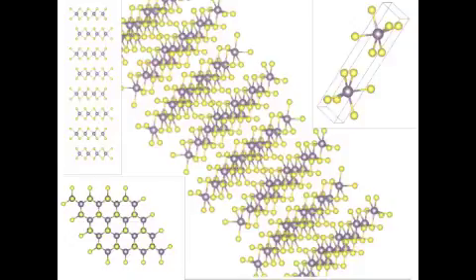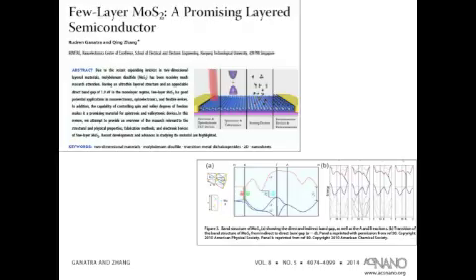There's a lot of interesting things about molybdenum disulfide as a 2D material. There's a lot of interesting ideas people have for building devices with it and how to use its layered structure because you can tweak its band structure in a lot of different ways, including based on the number of layers. Monolayer MoS2 is a direct bandgap material whereas multilayer MoS2 has an indirect bandgap. So there's a lot of interest in molybdenum disulfide and its properties and possibilities: optoelectronic possibilities, spintronic possibilities. I can't explain spintronics.